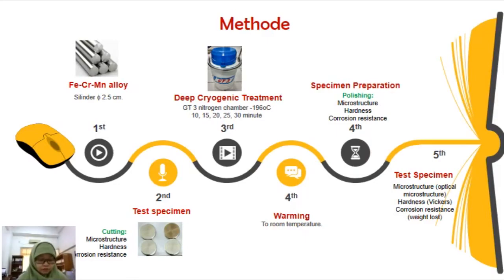The solid cylinder of the FeCrMn alloy was cut using a bimetallic band saw blade to make the test specimens into microstructure and hardness test specimens. The corrosion specimens were made based on ASTM G30. The deep cryogenic treatment process was carried out in liquid nitrogen at soaking times of 10, 15, 20, 25, and 30 minutes in a nitrogen chamber. Then the warming process is carried out to room temperature.